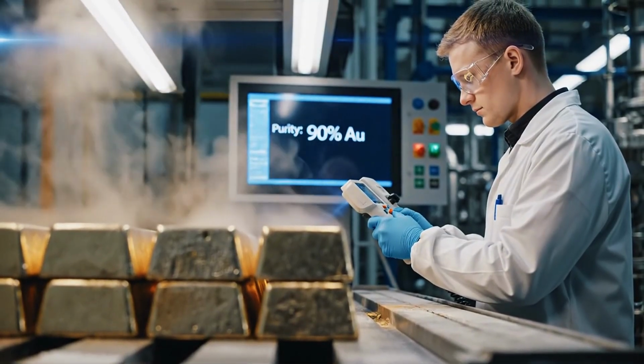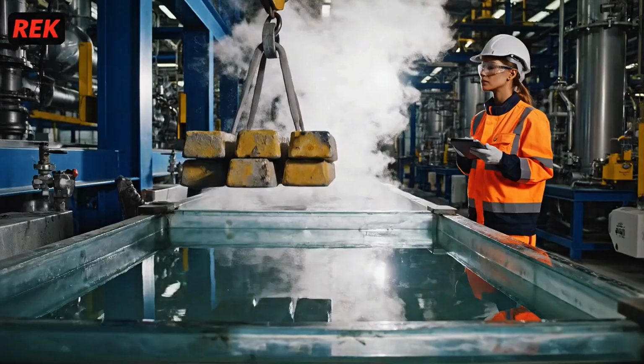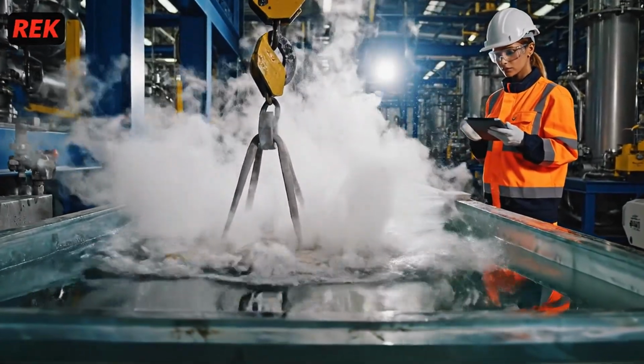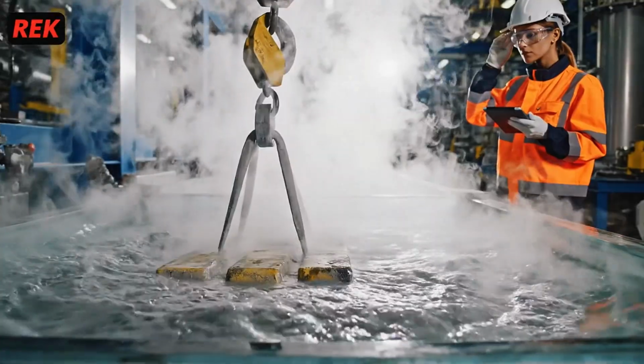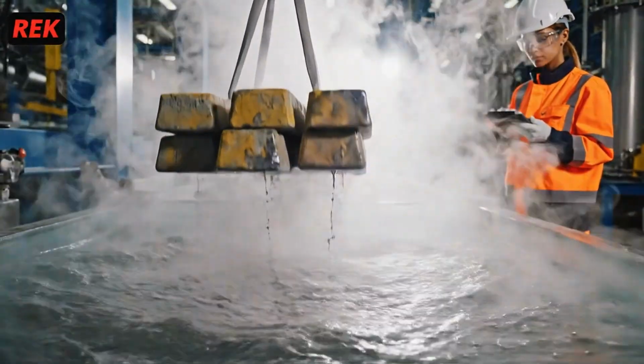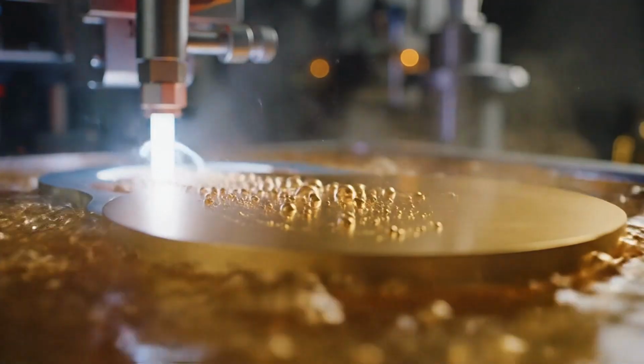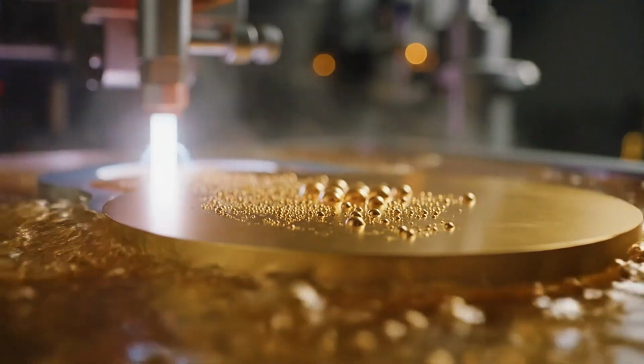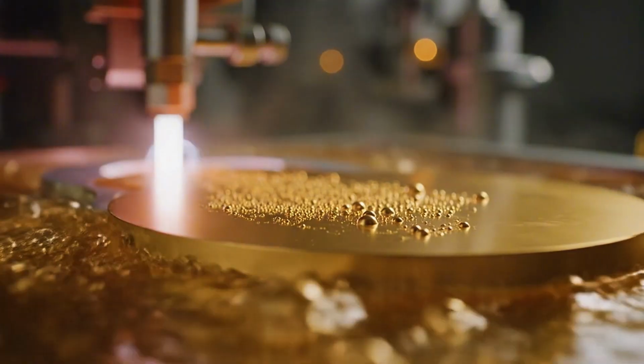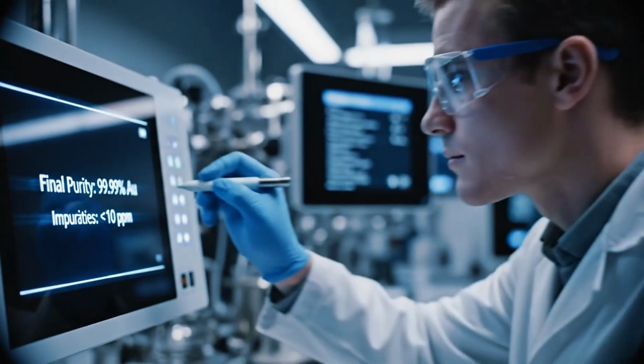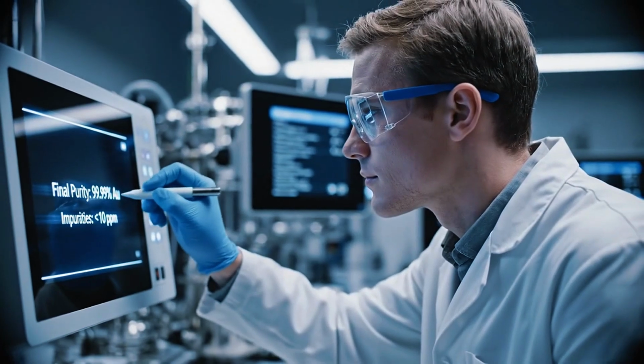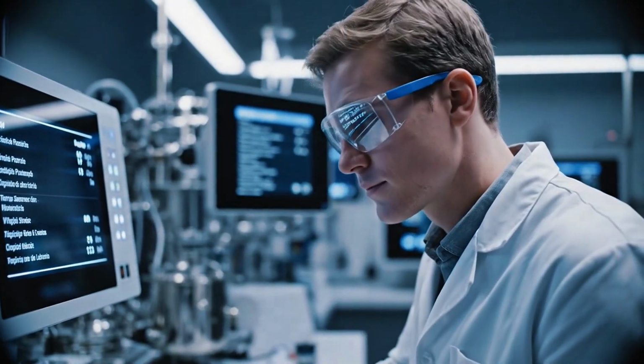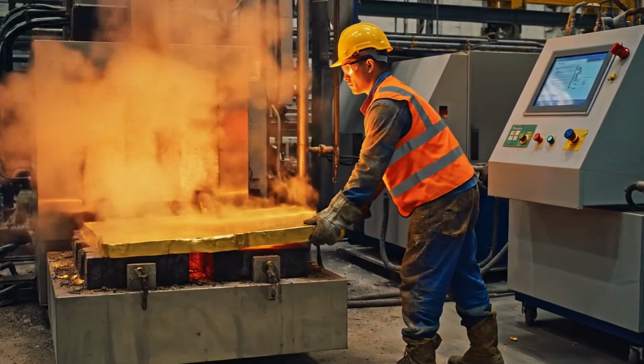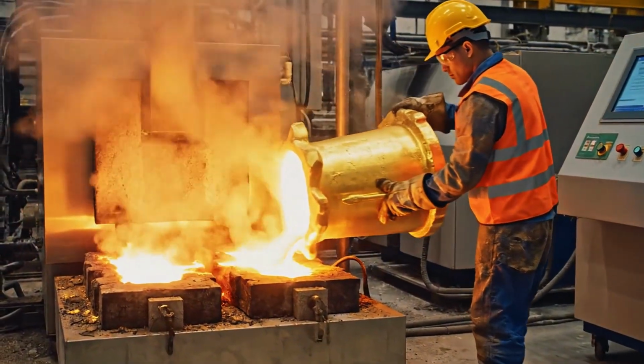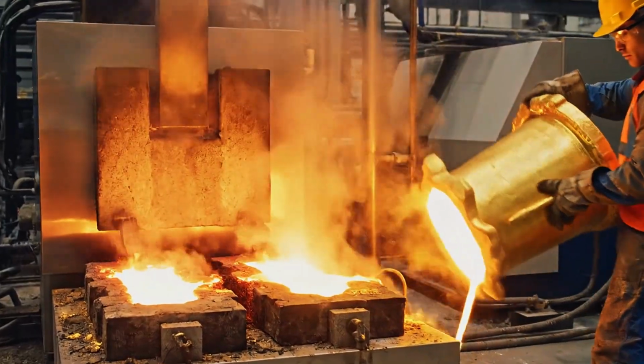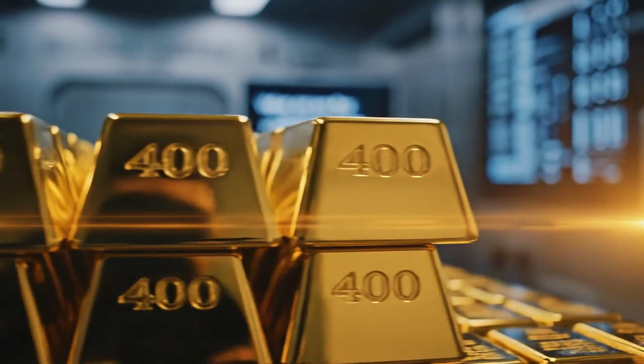The final transformation occurs in specialized refineries, where doré bars are dissolved in acid solutions and subjected to additional purification processes. An electrolytic refining passes electrical current through gold-bearing solutions, depositing pure gold onto cathodes with precision that achieves 99.99% purity, a level where impurities are measured in parts per million. This ultra-pure gold emerges as cathode sheets that are melted and cast into standard bars weighing exactly 400 ounces each.